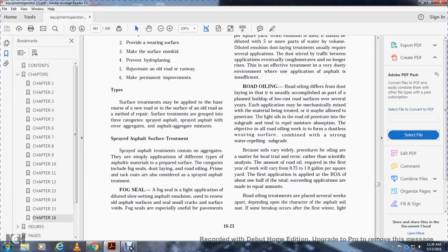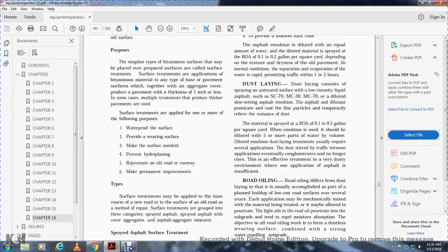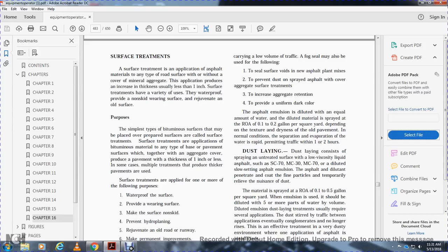Sprayed asphalt categories include fog seal, dust laying, road oiling, and primary and tack coats. A fog seal is a light application of diluted, slow-setting asphalt emulsion used to renew old asphalt surfaces and seal small surface voids. Fog seals are especially useful on pavements carrying low-volume traffic. A fog seal may also be used to: seal voids in new asphalt mix, prevent dust in sprayed asphalt with aggregate surface treatments, increase aggregate retention, and provide uniform dark color.